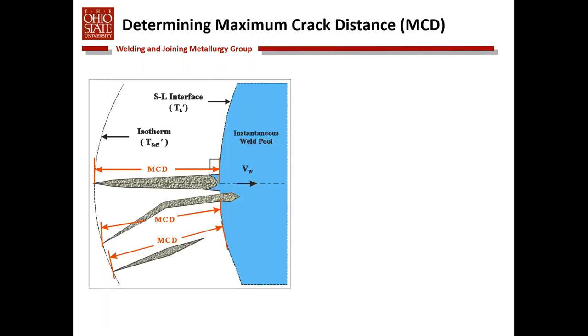So our approach at OSU is to measure something called maximum crack distance, where if a crack forms at the trailing edge of the weld pool, we basically measure the distance from the solid-liquid interface at the time of bending to the tip of the crack. The reason we do this is this represents the isotherm, or the temperature range over which cracking actually occurs. And so what we're really trying to get at is the temperature range over which cracking occurs as a measurement of the cracking susceptibility.